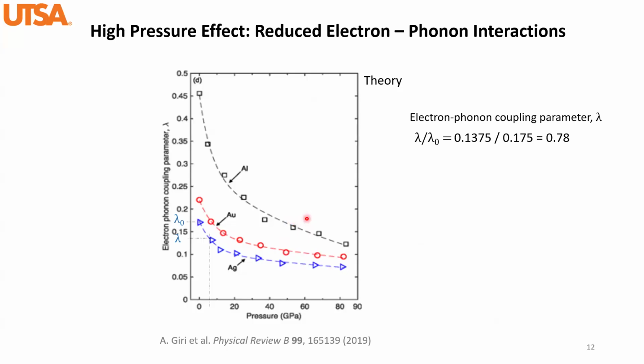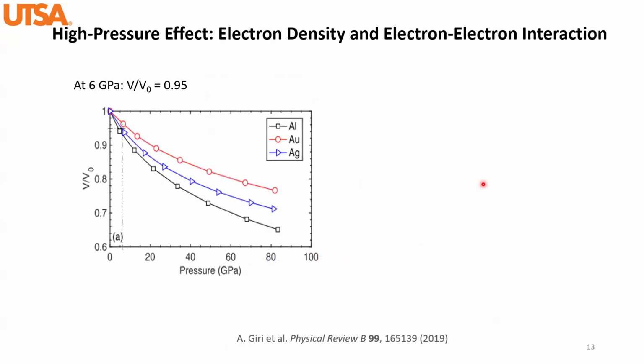First of all, we're really interested in the electron-phonon interactions. Reading this figure, at 6 gigapascals, we find that the electron-phonon interaction was reduced by over 20%. This is a very big drop when you consider plasmonic losses caused by electron-phonon interactions. Now let's take a look at electron-electron interactions.